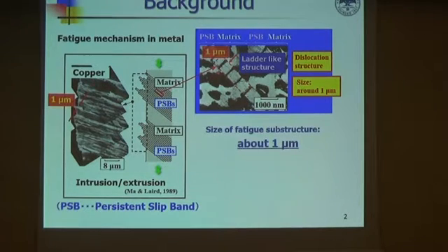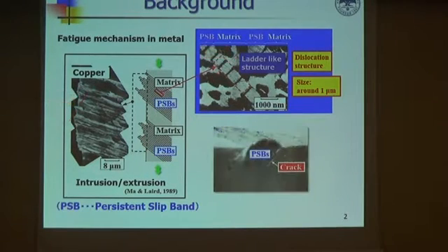It is widely known that the size of this fatigue substructure is about 1 micrometer, which is independent of material size. And it is also known that the PSB plays an important role in fatigue fracture because fatigue cracking is generally initiated at the PSB.